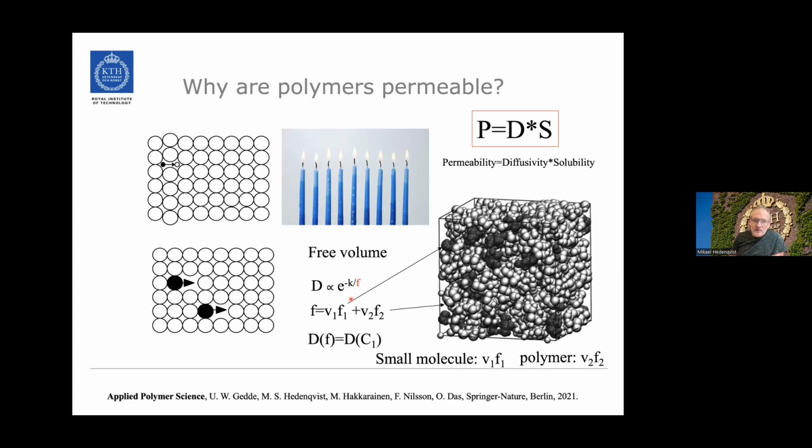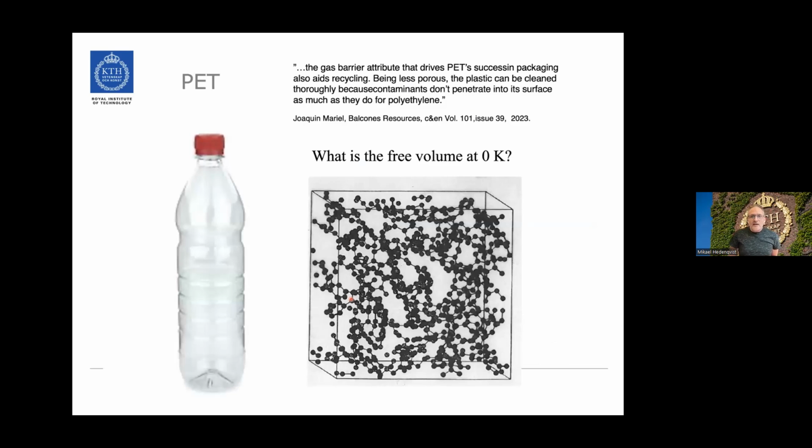To obtain the total free volume in water and polyvinyl alcohol, for example, then that's much more tricky. Then they are not really additive like this. But for a non-polar or hydrophobic polymer and a hydrophobic foreign molecule, it can be oxygen, it can be methane, then you can actually add those up. And the fact that they are not tight, that there is free space, creates different kinds of problems also.